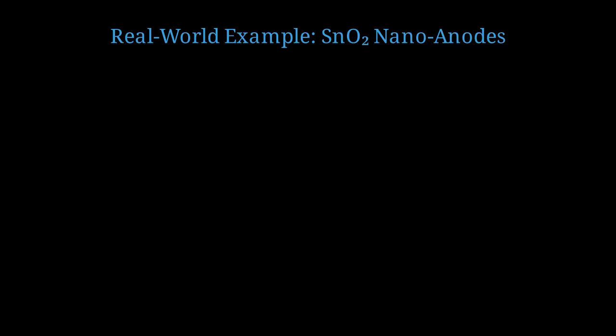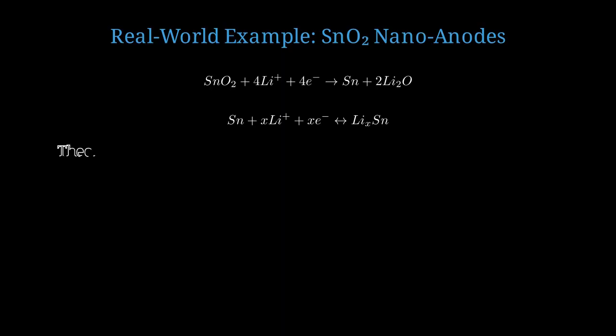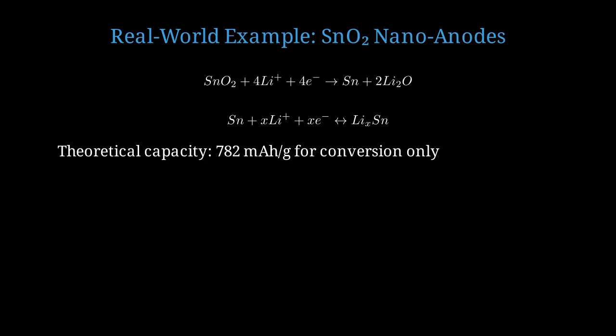Tin oxide nanoanodes. The reaction is tin oxide plus 4 lithium ions and 4 electrons gives tin metal plus lithium oxide. Then the tin can alloy with more lithium to form lithium-tin alloys, where X can be up to 4.4. The theoretical capacity for just the conversion reaction is 782 mAh per gram. With the alloying reaction, total capacity can exceed 1500 mAh per gram. That's 4 times higher than graphite.